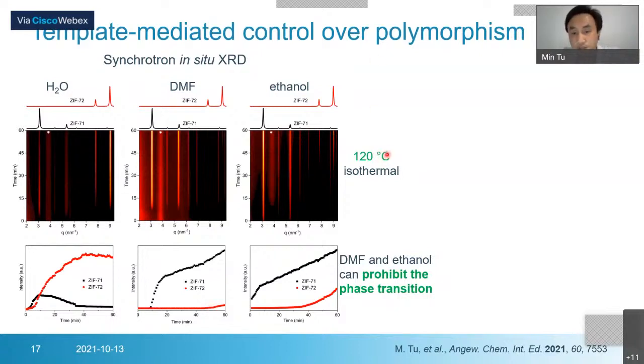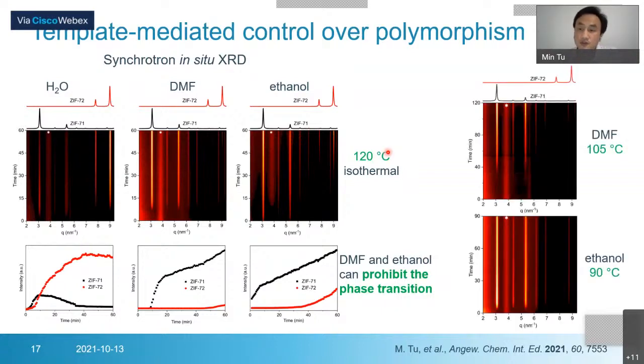We can see at 120 degrees C, it prefers to form ZIF71, but we cannot completely prohibit this phase transition. Then we lower the temperature to avoid this phase transition. We work, for example, with DMF at 105 and ethanol at 90. We didn't see any formation of ZIF72, and we can get a phase pure ZIF71 MOF film. Yeah, this is the first case of MOF CVD deposition of a MOF film with a template.